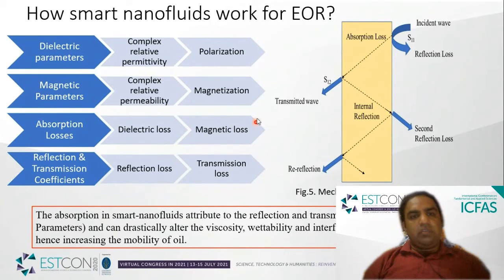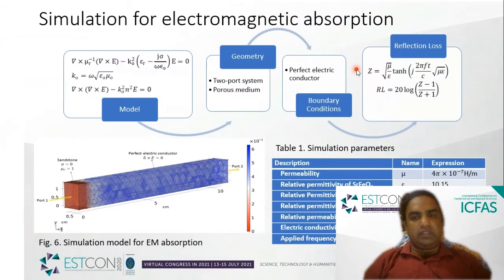So this absorption loss actually enhances the reflection and transmission coefficients, and is responsible for the alteration of viscosity, wettability, and interfacial tension of the oil and water. Therefore, we can increase the mobility of oil, because as we increase the absorption in this part, more and more particles in this reservoir will be activated. Activation means that they will affect the interfaces of oil and the wall of that reservoir, which can change the viscosity, wettability, and interfacial tension.